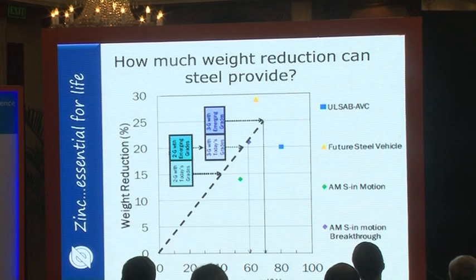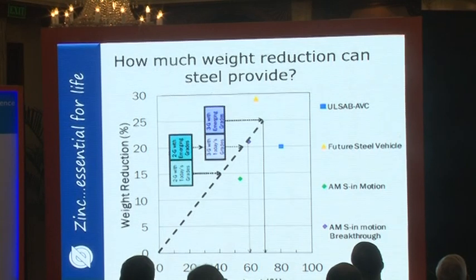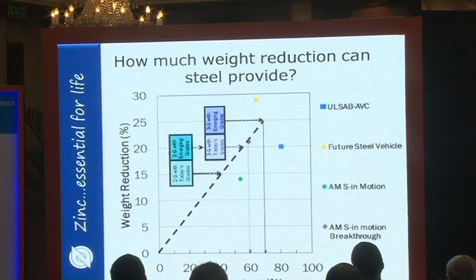And there's been a recent breakthrough in the development of third-generation steels. These are the austenite martensite steels. We have found a way, in the GAP program, of not only reaching the mechanical properties that are required, but also providing hot-dip zinc coatability of these steels, and that's not been shown before.